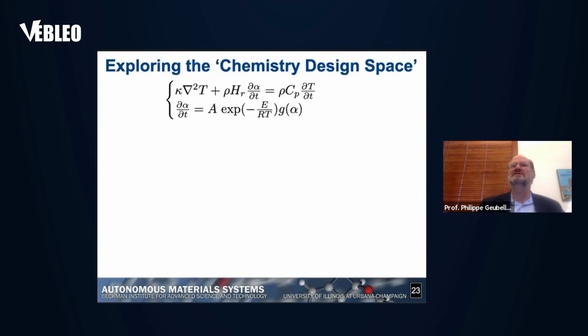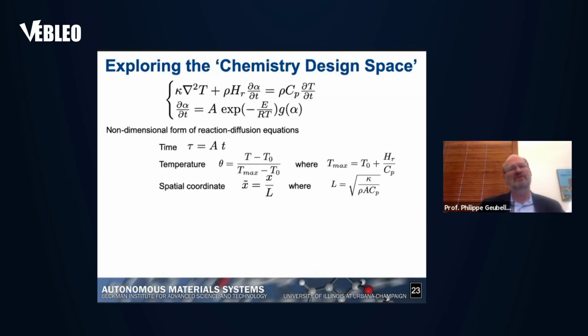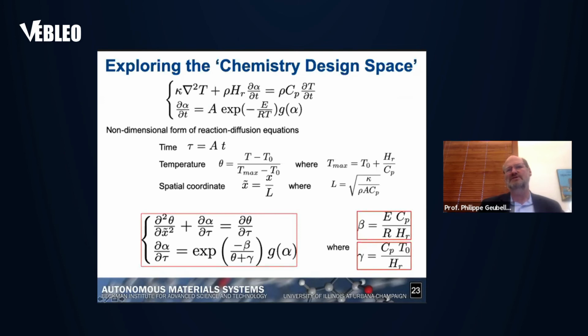By looking in more detail at these two equations that I mentioned, we can actually explore what we call the chemistry design space, right? So there are lots of parameters that show up in there, but if you actually perform a fairly straightforward non-dimensionalization of these equations and normalize the time by using this time constant A that shows up over here, normalizing the temperature by using the initial temperature and the temperature of the front, which is given by this, and normalizing the spatial coordinate using this particular length scale, we reduce these equations to non-dimensional form in which you have two parameters that appear.